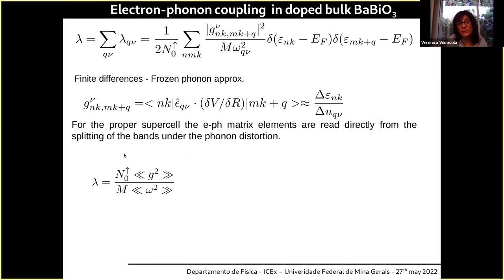In a simple way, you can see that the electron-phonon coupling will depend linearly on the density of states at the Fermi level, and then on this coupling of the electrons with the structural distortions. So you will have a larger lambda if you have a larger density of states, and also if you have a larger coupling. And there, you have the phonon frequencies involved in the corresponding collective mode.